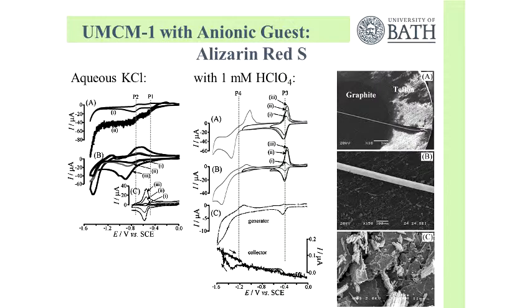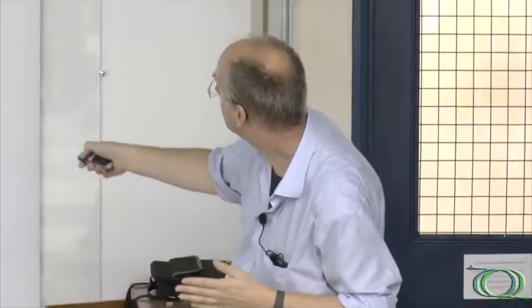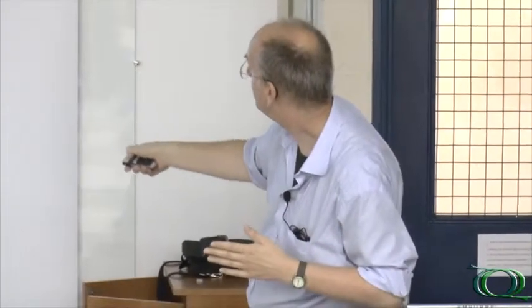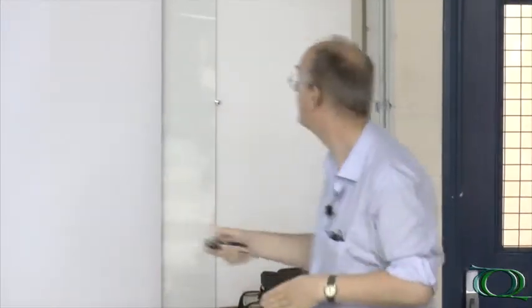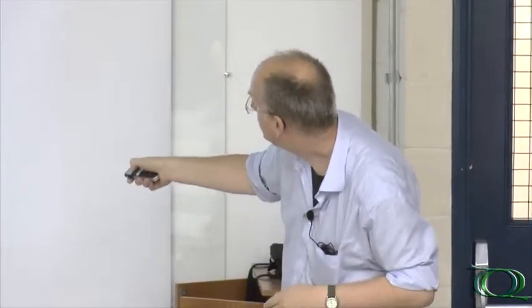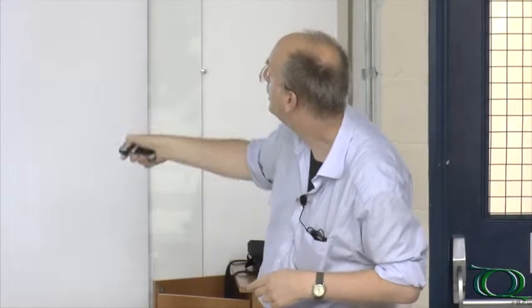When it's alkaline, then the reduction of this species in the pore actually is breaking up the solid and releasing the dye into the solution. We wanted to test this and we put a platinum wire over the surface. That's the carbon surface modified with the MOF. With this platinum wire, we can pick up the product. If something's produced, we can detect it on the wire. We can see that if we run such a voltammogram on the wire, we can pick up the dye. So the dye is released into the solution, breaking up the solid.